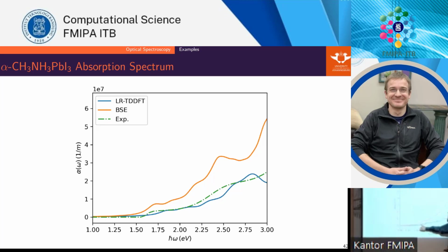But you see that the important thing is actually that we need to have this one done very well. This is the absorption edge. This is where basically most of the electrons are interacting with the light and can be producing electricity. And you can see that because we don't have the interaction between the hole and the electron, which is Coulomb interaction, it lowers the energy, right? So we need less energy to excite this. We actually get numerically a too high energy we need to produce these free electrons we can use for electricity. So that's bad, right? That's why we need to use BSE.